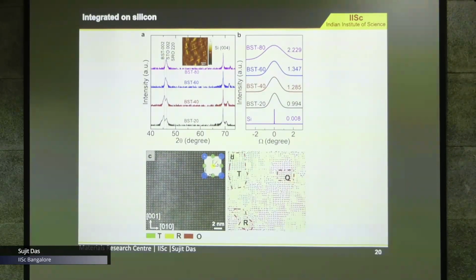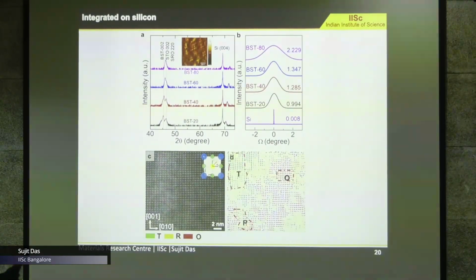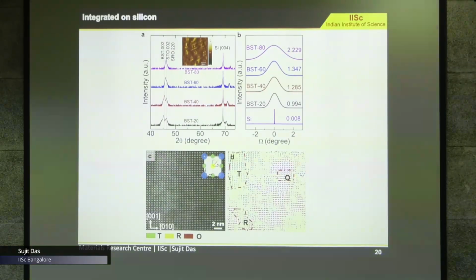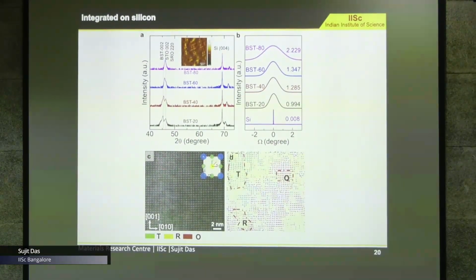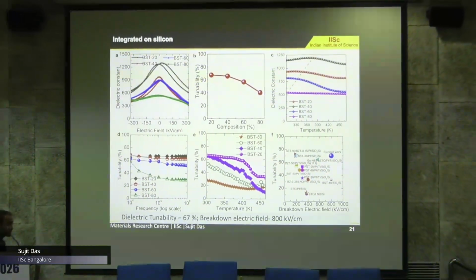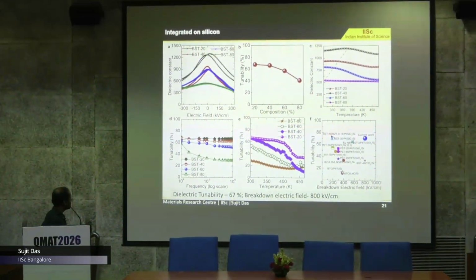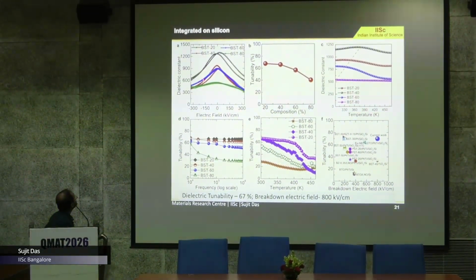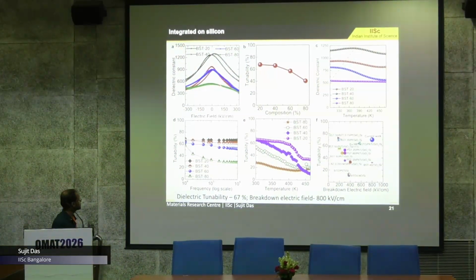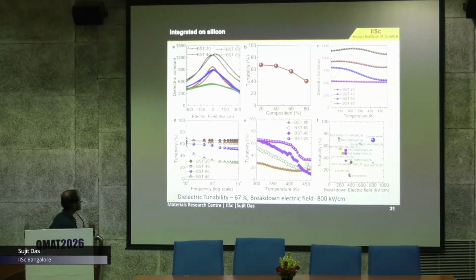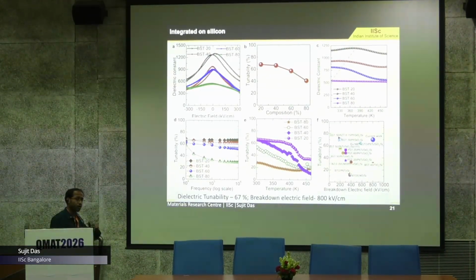For this BST20 particularly, if we take the high-resolution TEM image and the polar mapping, we can see that on silicon it also has a mixture of tetragonal, orthorhombic and rhombohedral phases. Further, we make devices on these samples, and we found again the BST20 showing the high dielectric constant with respect to the other compositions. The tunability is not as high as STO, but we found it around 70%, which decays with the other compositions.